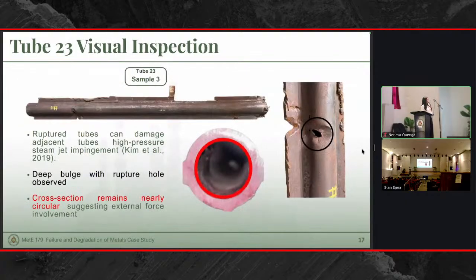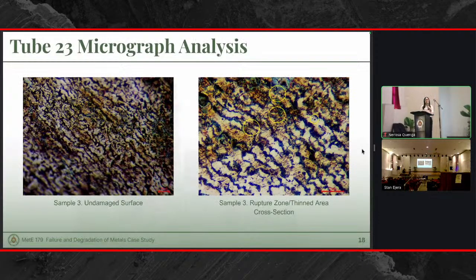We also conducted inspection on the bigger rupture in tube 23, and we can see that the bigger rupture has a deep bulge around it, and that the cross-section of this tube remains nearly circular, suggesting that the failure came from external forces. We conducted micrographical analysis on the cross-section of the tubes, and we can see that in the undamaged surface, there is no evidence of spheroidization.